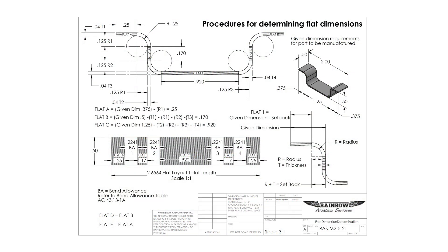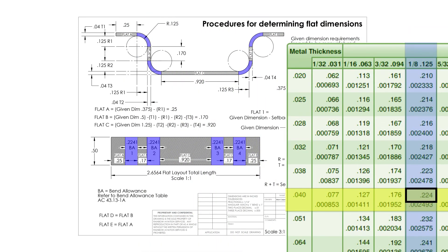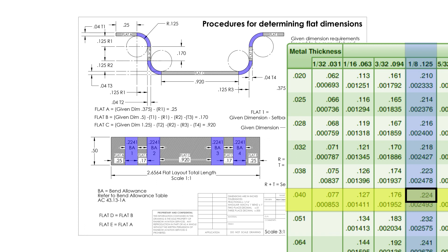When we prepare a piece of sheet metal for bending, we are doing what we call a flat layout. All of the sheet metal components are simply a series of flat sections and bends. Prior to bending up a sheet metal part, we will get out a piece of scratch paper and formulate the layout similar to the part we are going to manufacture. We will lay out each flat section with the bend allowance required for each of the bends. Because the bends are 90 degrees, the material thickness is the same, and the radius for each bend is also the same, we only need to calculate or look up the bend allowance one time.